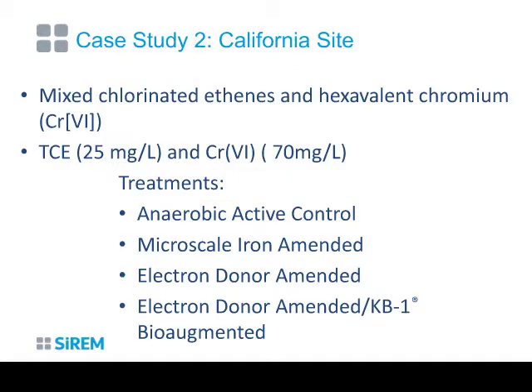The next case study is a site in California where we are evaluating a bioremediation approach versus an abiotic degradation with zero-valent iron. What we looked at here was trichloroethene at 25 milligrams per liter, which is pretty high for some sites, and hexavalent chromium at 70 milligrams per liter. The treatments that we assessed here were intrinsic degradation with an anaerobic active control, microscale iron looking at the ZVI application, and an electron donor with and without bioaugmentation.